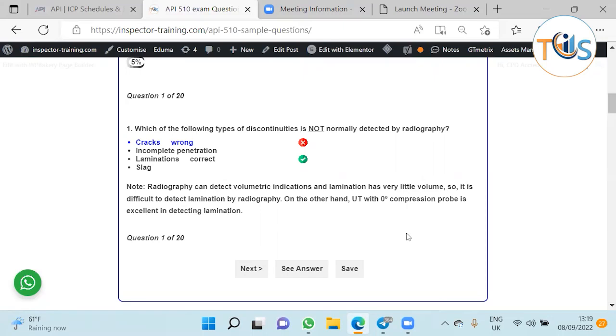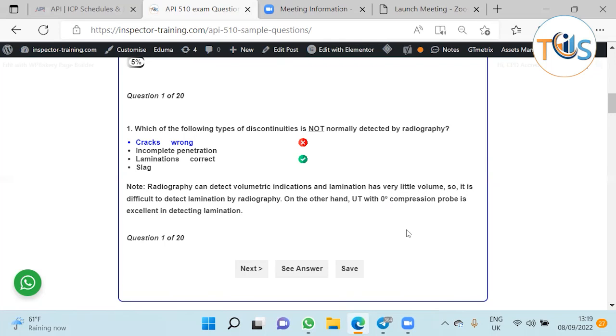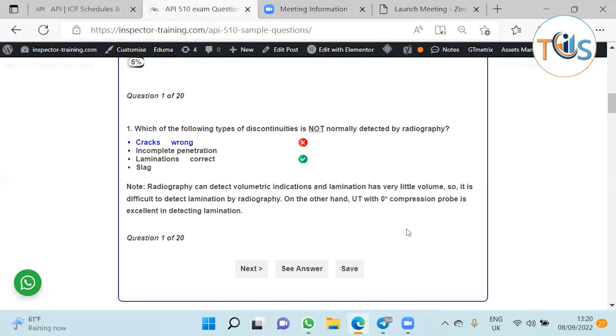As a result you see a lighter version on the radiographs. The only exception would be gas tungsten arc welding where you have tungsten inclusion of the electrode tip. Tungsten is a very dense material, denser than practically any other base metal, so you see them as lighter. In case of lamination, there is not much space between two parts which are not fused during pipe or plate manufacturing, so it's very hard to see lamination in radiography.